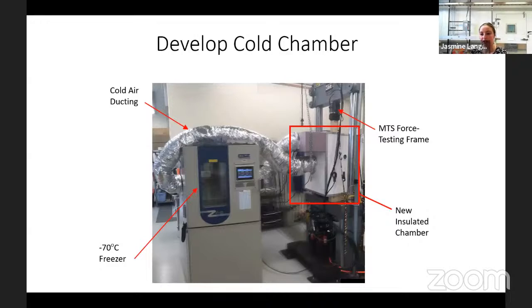So we built basically an environmental chamber to test these. We have our MTS machine on the right, and then our insulated homemade environmental chamber. And then we hook that up to a freezer that goes to -70 degrees Celsius. And I believe when we were testing, we set it to -40 degrees Celsius so that the testing chamber would be about -10 Celsius when we were testing.